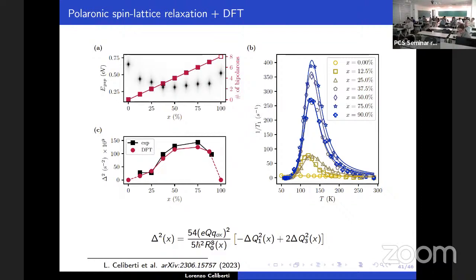So this model was, this should be this delta Q1, delta Q2, Q3, basically an average amplitude of this fluctuation when you have the opening. So imagine you have polaron, non-polaron, so you have different Q1 on the two sides, different Q3. During the opening process, this lattice is oscillating, so you take this as a kind of amplitude of this oscillation. But it's temperature dependent. The point is that the level of detail in which this model has been developed does not account for this, because to evaluate this, I just evaluated them from DFT calculation, which is basically zero temperature.